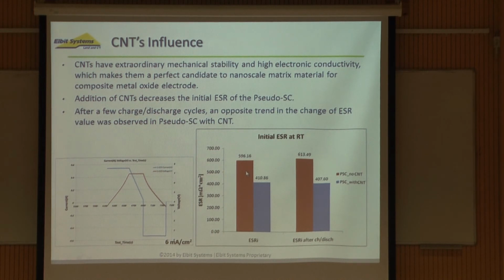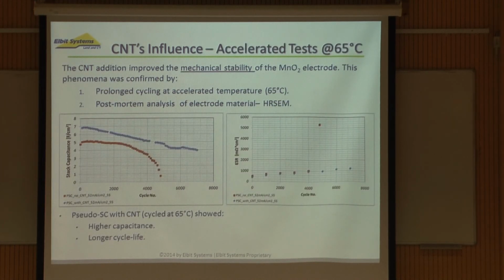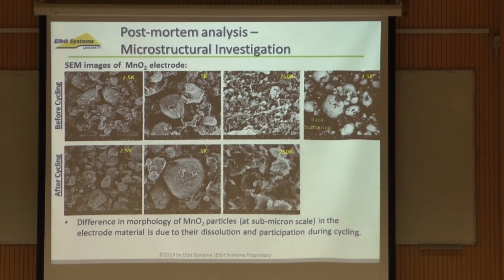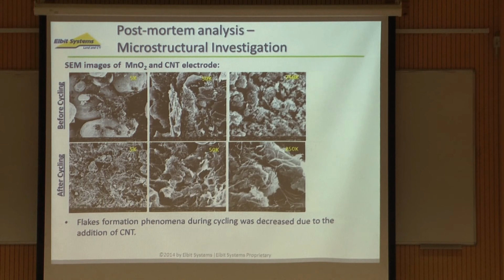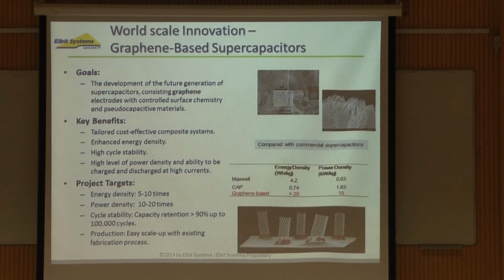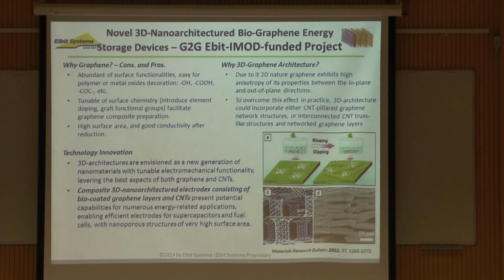And then we saw that the initial ESR was decreased, and what was more pronounced was the prolonged cycling at accelerated temperatures. We did some post-mortem analysis, and we saw that the degrading phenomena, the failure phenomena, which is the dissolution and this flake phenomena that comes due to the dissolution and precipitation of the manganese dioxide grains due to the cycling, was somehow reduced, because you have these CNTs serving as a strengthening net. This is our assumption, that they keep the cathode together.